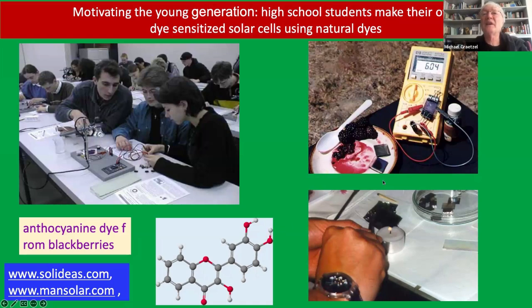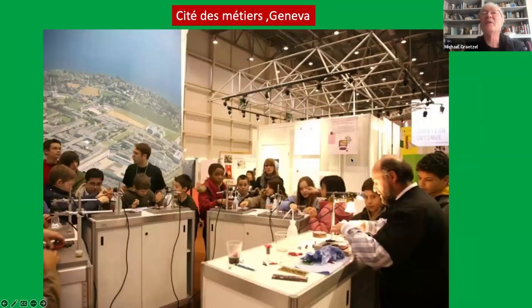So if you dip the TiO2 film, which you see here, in the pulp, you smash the fruits and you make it. If you dip them, there will be an uptake of the dye, and you can wash the cell. It will be highly colored, because of the mesoscopic structure, which has very high internal surface area. And here you see the voltage is 604 millivolts. That's not bad at all from an indoor or outdoor measurement.